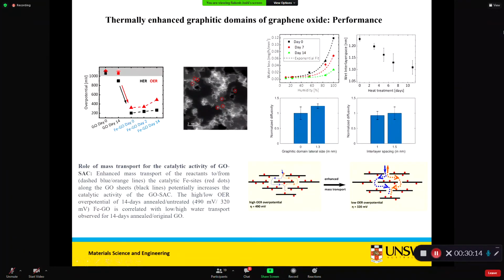But if you further anneal the Fe graphene oxide membranes, the performance deteriorates. So you can say this sample, which is the best electrocatalyst we made here, is as good as iridium oxide in the OER performance. It's 320 millivolt here. So this is as good as the commercial benchmark, which is iridium oxide.